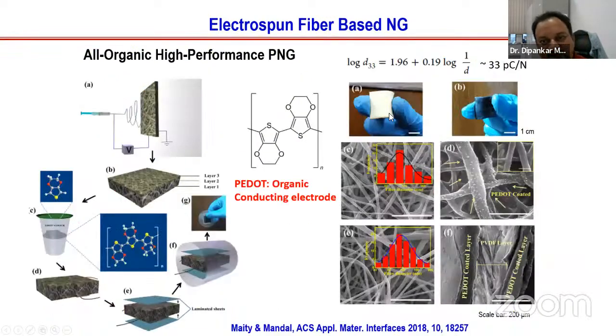The problem with this electrospun fiber is, you see this image, it is very spongy and air permeable. If it is air permeable, how will you make the electrode and the device? You have a piezoelectric nanofiber mat, and you have to make electrodes on the top side and bottom side. This is a simplistic device structure. Now if you deposit gold, silver, aluminum, or any metal, it will not be compatible because this is air permeable,